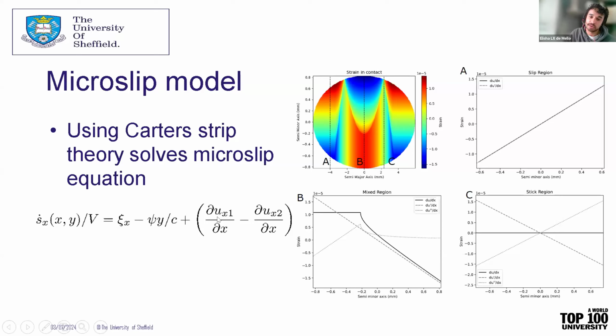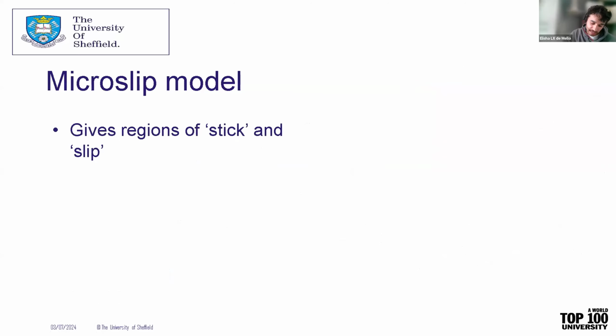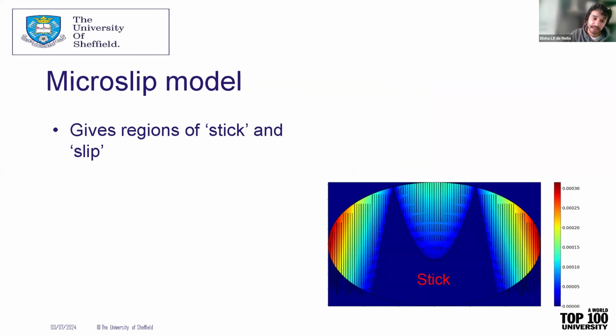And quite simply, all Carter's strip theory does is split the contact patch up into lots of little strips, and then it establishes boundary conditions for each strip, and it says that it's a steady state system. The system's solved for equilibrium, and it solves the strain so that equilibrium is maintained over the entire contact patch. So I implemented this method, and I found that it gives you this. This is a classical observation that we get over a contact patch. We get regions where there's no slip, and we also get regions where there's constant slip and high slip, due to that interplay of geometry and strain that I talked about.